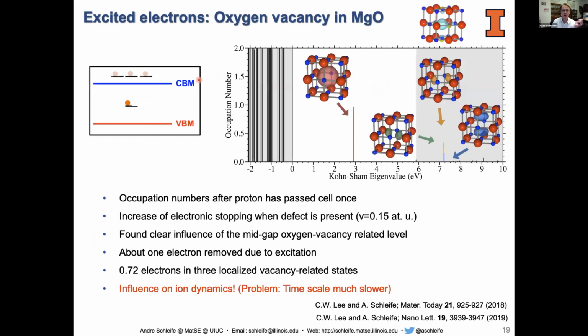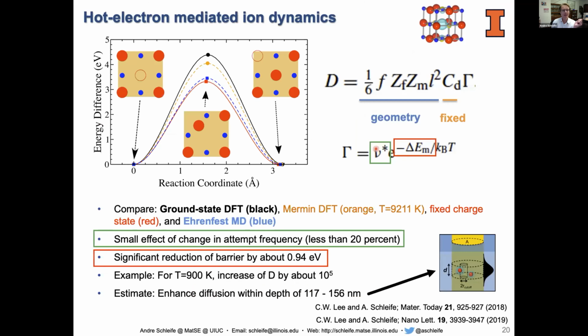And so in this case, if we impose these occupation numbers that we got from our time-dependent DFT simulation, in the transition state theory, we see the barrier drops by about 0.94 electron volt. So that's a tremendous drop, especially given the fact that diffusivity of these oxygen vacancies is determined by this exponential law here, right? By this Arrhenius law. So this barrier enters in the exponential, so a 1 eV drop is big.